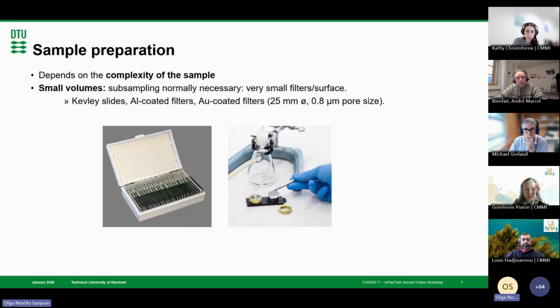What's specific to the LDIR is the kind of filters you have to use at the end. What goes into the instrument is the black support that you can see on the right normally. And these are aluminum coated filters. These filters can also be coated with gold, but of course this would be much more expensive. Aluminum coated filters are also quite expensive, but it gives the best results. These are really small circular filters.